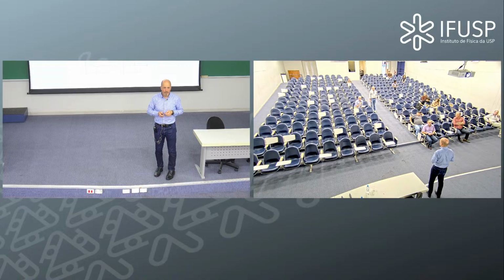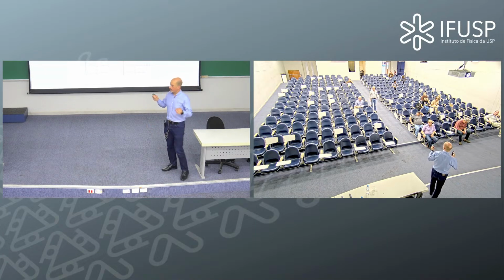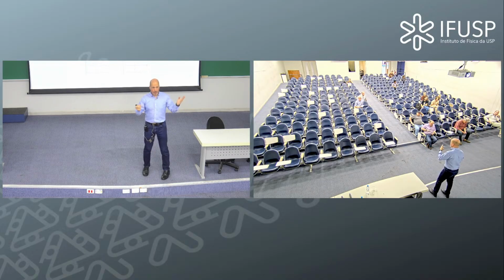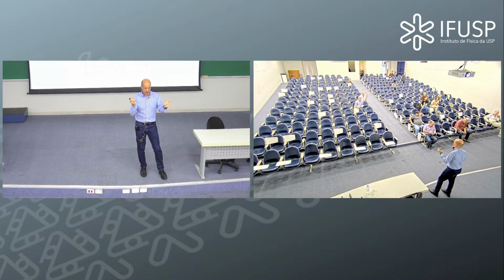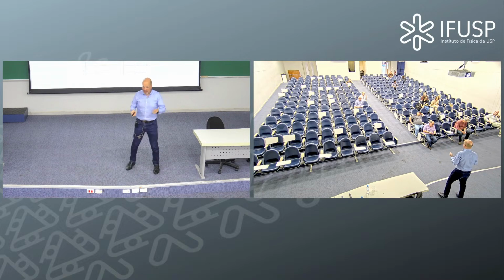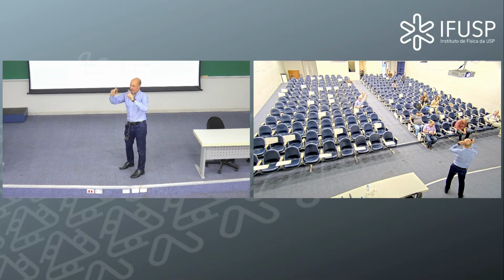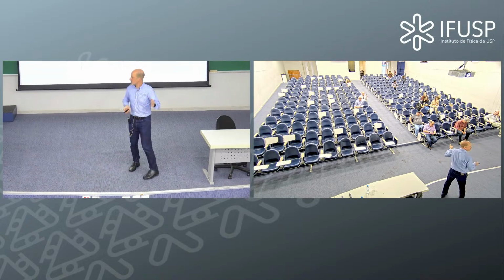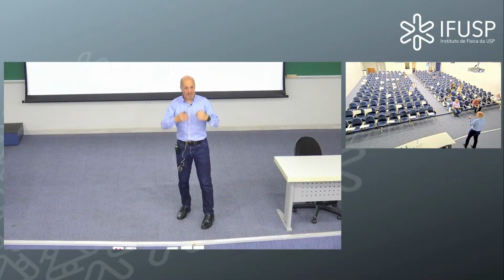So for the 3D models, the basis is the same. Basically here, you are only improving the geometry. The message I understood is that basically you recover the 2D, and this is it. Am I right? Yes, so for example, when you want to assess the microstructure, what you do in 2D is you have a section through grains, and you look at certain diameters, or how large the distance is between individual grain boundaries. If you do that in 3D, it's a completely different story, because in one direction the distance is short, but in the other it is large. So there are these geometrical issues that sum up and in the end lead to a result that is not bad, but not as precise as the 3D case.